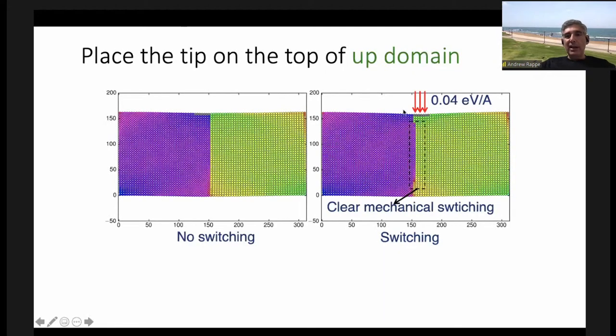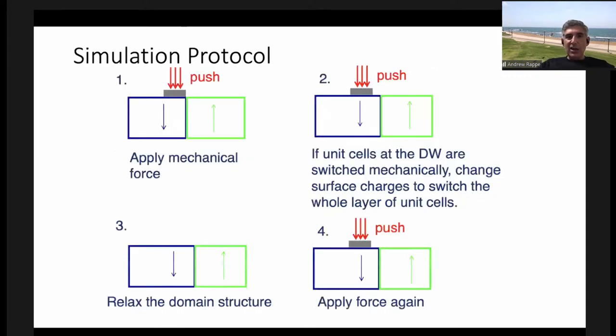And so now this is a case where we push, and you can see some of the unit cells have switched. This is enough pressure that we're starting to get mechanically induced switching, reproducing the results from the experiment.